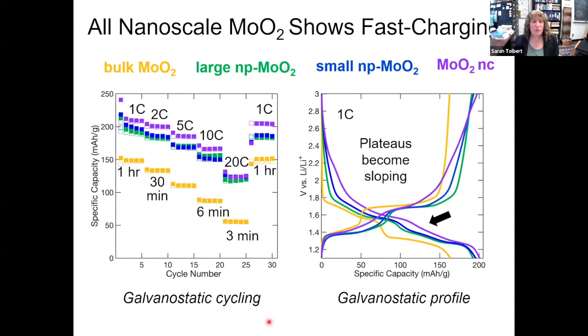Now we're going to look at how fast they charge. And we're doing something called galvanostatic cycling, which is constant current cycling. And what we see is that in purple, the smallest material has the highest capacity. And I have these numbers, 1C, 2C. These are charging rates. So 1C is charged in 1 hour. 2C is charged in 1/2 an hour or 30 minutes. 10C, 6 minutes. 20C, 3 minutes. And what we see is at all these rates, the smallest things keep the most capacity. The bulk in yellow shows the least capacity, and the medium-sized ones are in between.